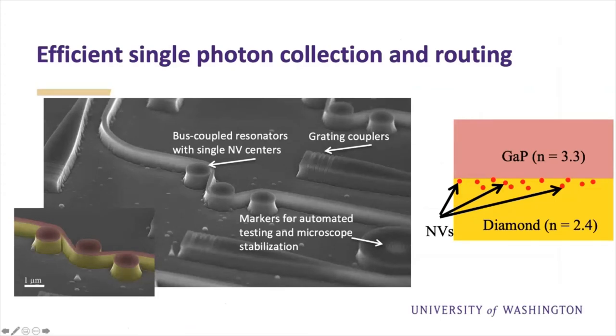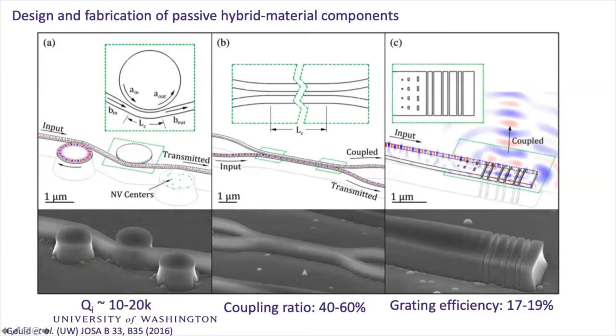And so this is an example chip where we have NV centers that we've created. And in this particular case, when it emits, we come back to here, this is actually a resonator. And what happens is when the NV center emits a photon, it emits into this mode, and that photon bounces around until it can then output into the waveguide and be routed on the chip.